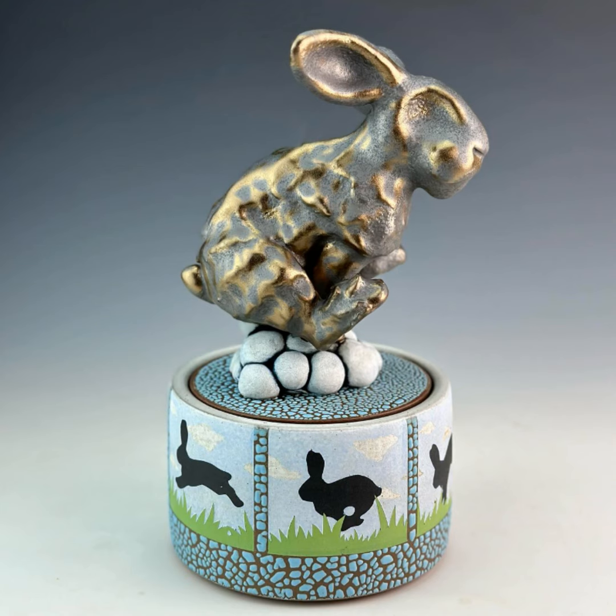Here's another little idiosyncrasy of that lichen glaze. If I don't wait long enough for the liner glaze to dry, at least 24 hours, the lichen glaze will all fall off in the kiln as it's heating up, because for whatever reason, the pot has to be bone dry again before I can glaze again. Sometimes I have tried to push things, if there's a market coming up, and maybe I'll put it in the kiln for a couple of hours on 200 to get it to dry a little bit. I think it's dry and it wasn't, then I just wind up with a kiln load full of lots of shelves to chip. So I have learned over the years just to let ceramics dictate what my schedule is.